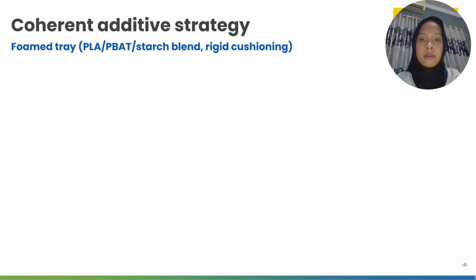For the tray M, the additive package is AO plus low dose chain extender like epoxy multifunctional, compatibilizer, PLA, PBAT, starch, nucleation aids, and rutile titanium oxide plus UV fast pigment. And it's coherent because chain extender plus compatibilizer improve the melt strength and toughness, and stable foam keeps the bright appearance. Tray M reduces the dust and shock, but compost mineralization risk increases, and starch is still moisture sensitive, so we must validate the ESD and aging.